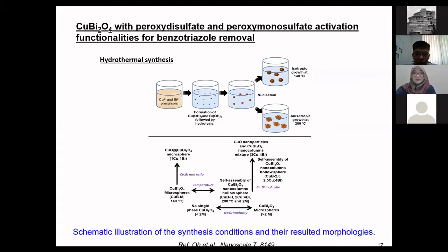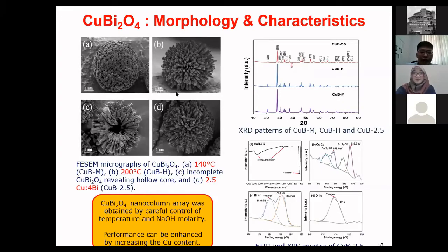And for this catalyst, we designed it using a hydrothermal synthesis method. This method is very good in controlling the morphology. So this is our result. This is what we get. You can see that when we control the temperature and NaOH molarity, we can get a form like this structure, which is very interesting. And of course, having this morphology, if it's useless, then it's not very practical, right? So we compare it. If you don't control the reaction, you will get this sphere. We compare with this sphere-like structure. So we compare B and A.